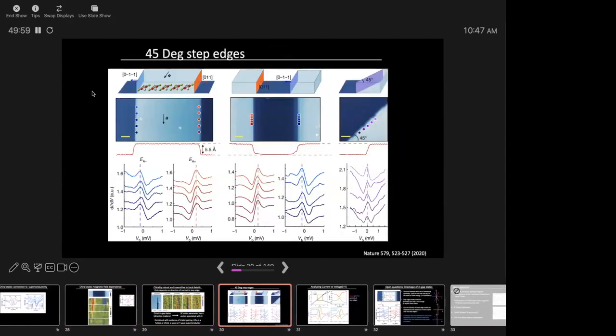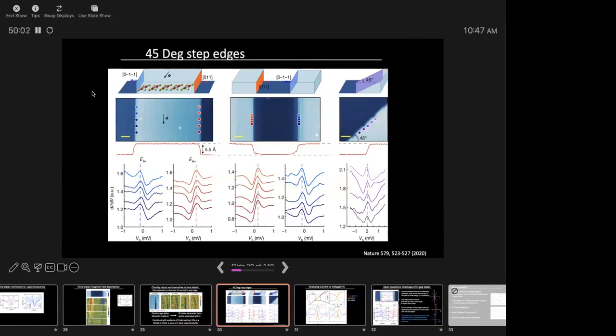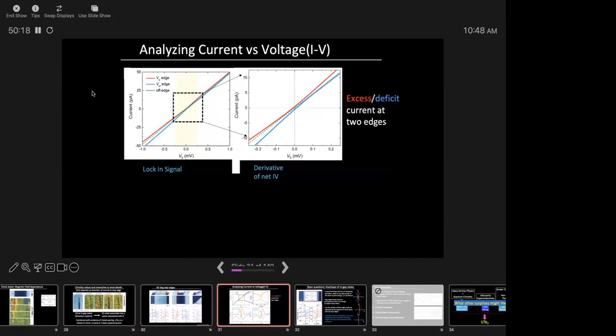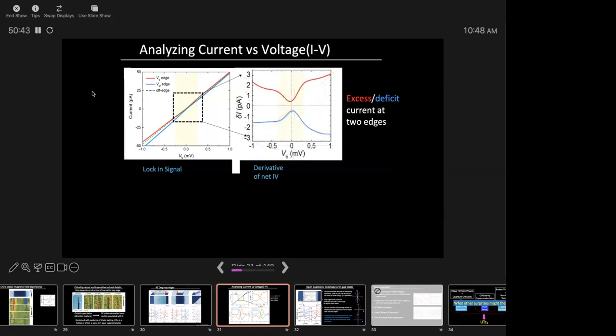Because I don't have time, I'm going to go through it quickly. We also found 45-degree step edges, and there you see a beautiful particle hole symmetric feature right at zero energy. You can call this a bound state if you like, but then these, I don't know what to say. One last thing before I move on to the charge density wave, which is really interesting. If you ask what the IV looks like, it looks very interesting. This is an IV on the edge, on the two step edges. If I just subtract a background straight line, then what it looks like is this.